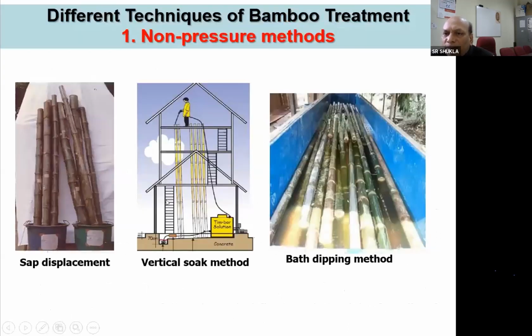These are the different ways by which bamboo can be treated. First is the non-pressure treatment, like sap displacement, very easy and without any investment. We have to take the chemical in a bucket and put the green bamboo in this, and after some time you reverse the bamboo. Because of this sap displacement, the chemical will diffuse inside the bamboo, and bamboo can get treated, but it takes time and